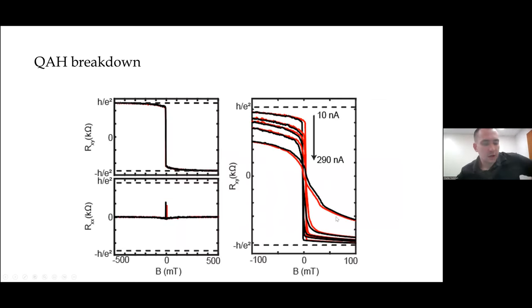Right, so all of that was interesting, but those are properties of Chern insulators that we more or less expected or already knew about. The main point of this section of the talk is actually a new set of phenomena that we studied in this system. Many of these interaction-driven phases have critical currents, or some threshold current at which they're degraded. These quantum anomalous Hall systems, these Chern magnets, are no different. There is a current or voltage bias threshold at which we see degradation of the quantization of the anomalous Hall resistance, and we see increases in Rxx.